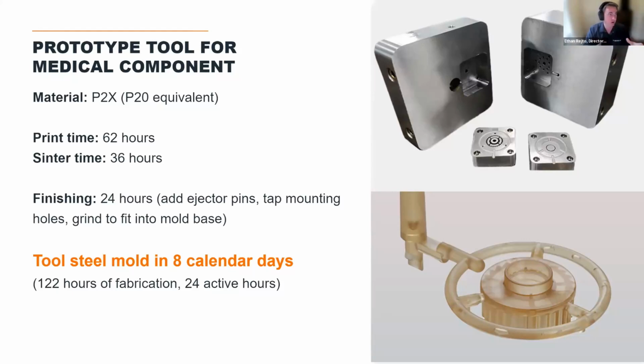Which is pretty incredible to think about, being able to produce a tool steel mold in just 8 calendar days to shoot acetal and Radel and mold hundreds or thousands of parts, no problem. So 122 hours of total fabrication, but only 24 of those hours were active. The printer and the furnace are going to run in the background. They're going to run with no input.